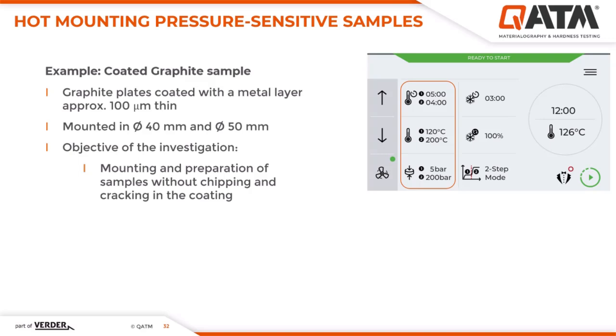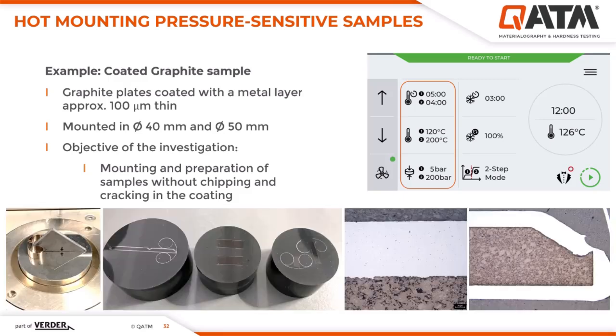In this case, the sample was a graphite plate coated with a very thin metal layer of about 100 micrometers. The goal of the laboratory task was to mount this material combination and to prepare it without chipping or cracking, with special attention given to the examination of the thin metal layer. This approach was intended to ensure that the sample preparation process would not influence the results.